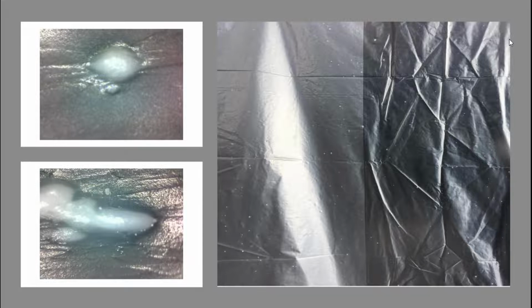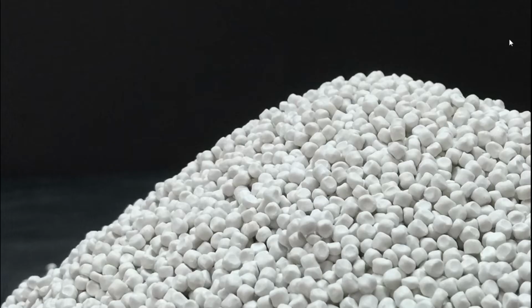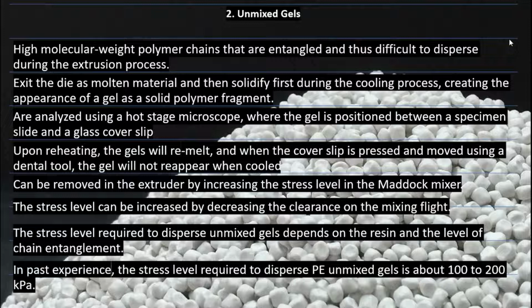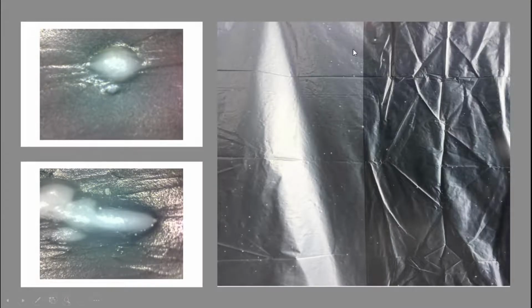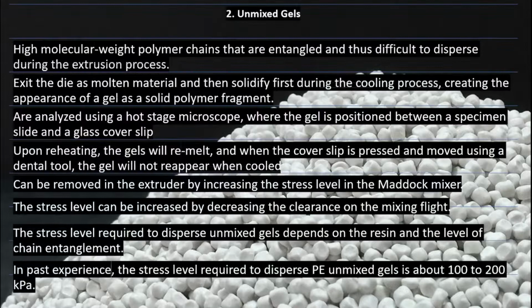In order to analyze these types of gels and differentiate them from the other types of gels, we use a hot stage microscope, where the portion of the film that has a gel is positioned between the specimen slide and a glass cover slip. Then the gel is melted by increasing the temperature, and when you reduce the temperature, the gels will recrystallize. Upon reheating, the gels will remelt, and when the cover slip is pressed and moved using a dental tool, the gel will not reappear when cooled. So it means that the stress applied by the dental tool has disentangled these chains.